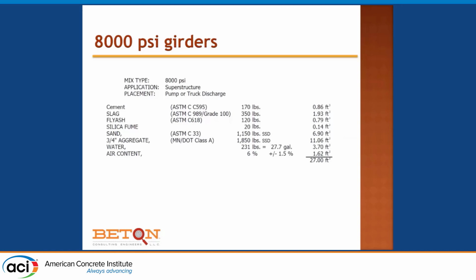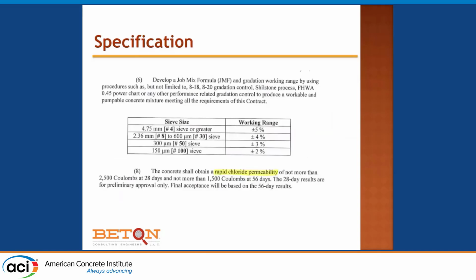We also have a particular blend of Class A aggregate that was custom crushed for the project, because of the advantage of having your own aggregate sources, and it is very well graded, with the exception that there is a gap at the half inch. We like gap graded mixtures because we can pack them together. The cool kids call them tarantula curves, but gap graded mixtures, if you can control them, pack together very nicely. And the goal here, the mix is designed to have as little cementitious material as possible, meeting the other requirements, because of course shrinkage is one of our requirements.